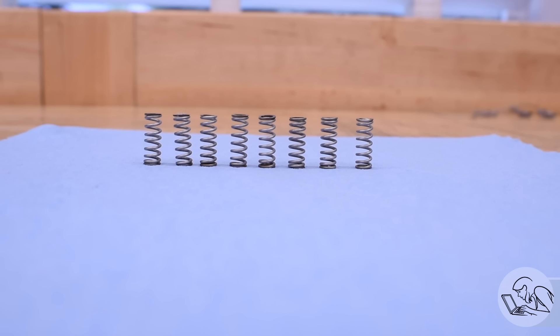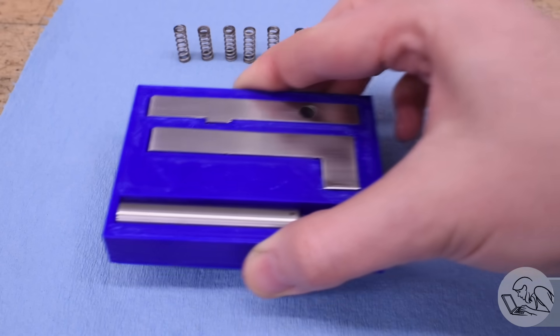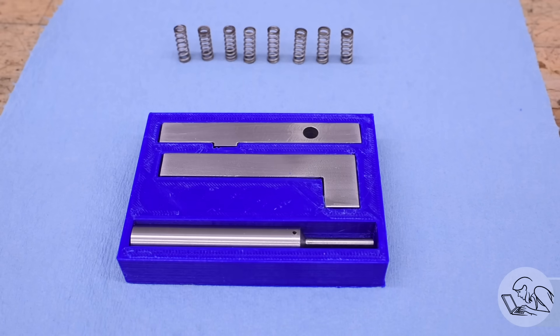Here's roughly the result that you're aiming for. I've got the number of open coils that I wanted which is six and then a half to one full turn of closed coil at each end, and everything is ground flat so the closed coil tapers into the open coil below. With some care and practice this process is also nice and repeatable. So these eight springs are all within five thousandths of the same length and they all have the correct number of open coils and closed coils on them. All these tools should be reusable as well. I'm not going to tell you you have to 3D print a storage case for them but it doesn't hurt. You may have to turn additional mandrels for other springs or you may have room on that one to turn other diameters, but if nothing else certainly the wire feeder and the seat grinder can be reused for all sorts of other springs that you might need to make.